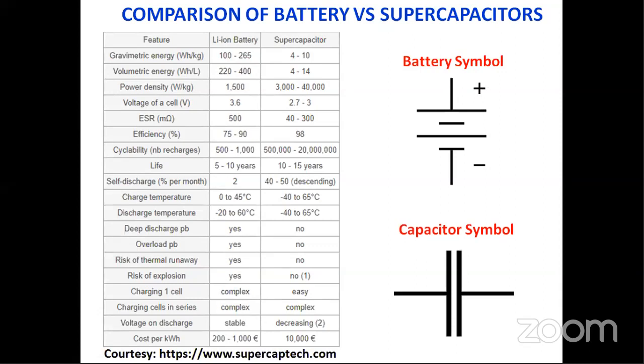But in the case of a supercapacitor, if you charge it and leave it for 3 days without any disturbance, and then look at the potential, the state of charge of the supercapacitor will be nearly 5% or less. Which means it's self-discharge. The self-discharge will be very high for a supercapacitor. It is a major drawback of the supercapacitor, of course.